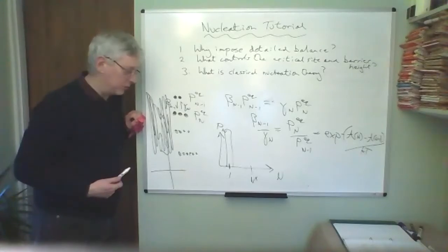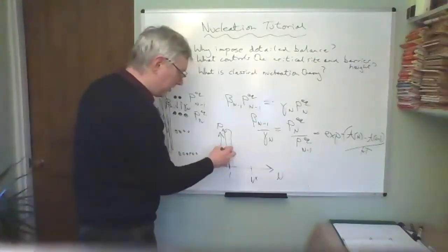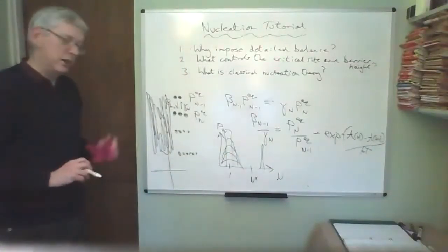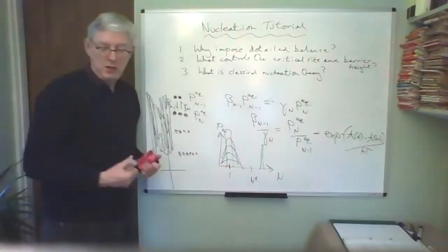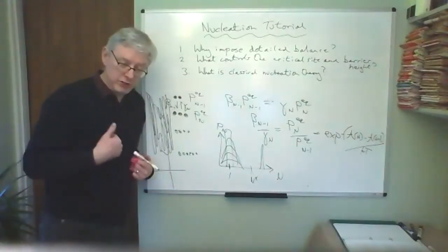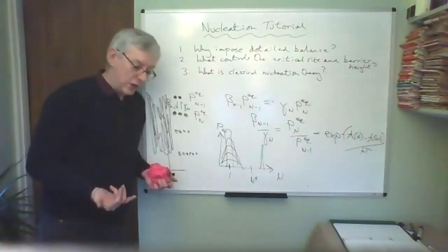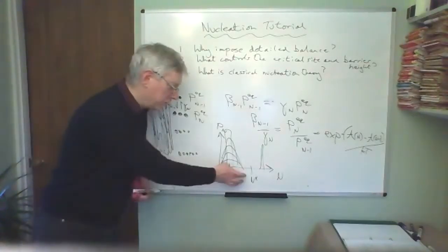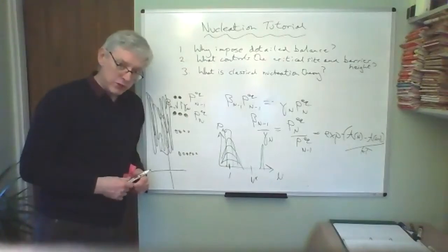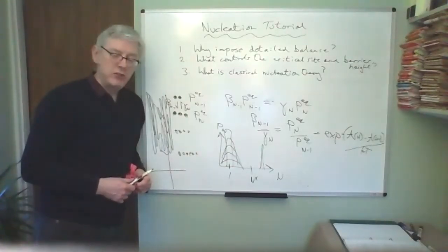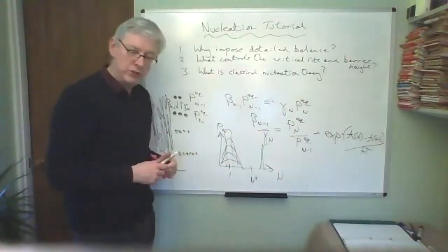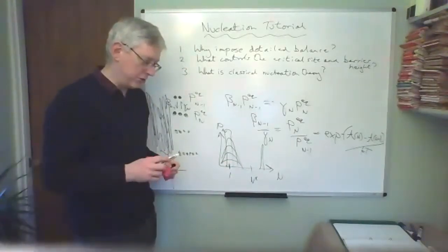And literally so. The probability doesn't move, but then it moves rapidly across the barrier. There is a barrier at the critical size. And that's what nucleation is. It is the incubated stochastic crossing of a critical zone in macrostate space at a rate which is to be determined. But it is a rapidly changed state that you get a condensation in the example of my raindrops out there.